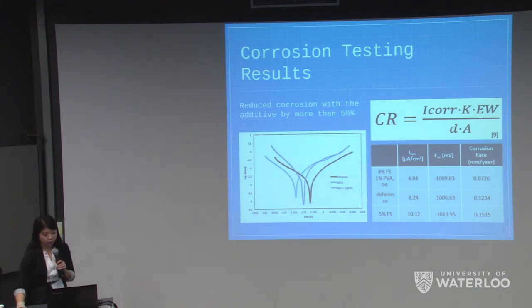The corrosion current is shown to be reduced more than 50% with the addition of fumed silica and PVA compared to that of the liquid electrolyte, and the gel electrolyte with only fumed silica as well. The currents are converted into a corrosion rate to give an idea about the degree of corrosion using the equations, where EW is the equivalent weight, D is the density of the electrode, A is the surface area, and K is a constant to convert the current into corrosion dimension per year.